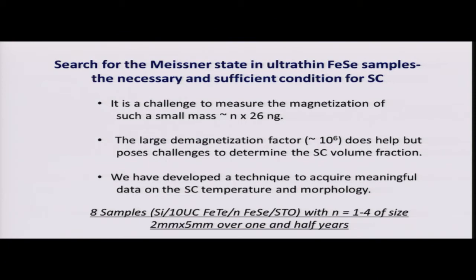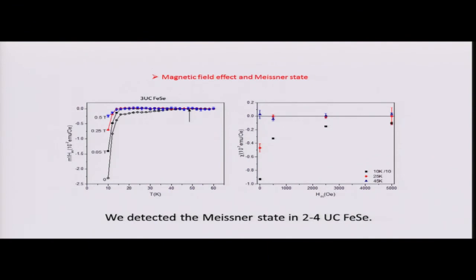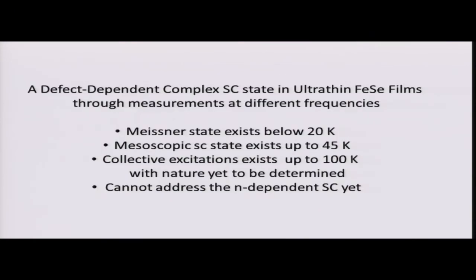One of the definitive signatures of superconductivity is the Meissner effect. So therefore, we decided to look at the Meissner effect. Indeed, we saw the Meissner effect in this material, as you can see in this magnetization as a function of field measurement. I'm not going to bother you with the details. So it is superconducting, but that Meissner effect only exists below 20 degrees Kelvin approximately. And then up to 45 degrees Kelvin, we saw mesoscopic superconducting states exist in this material. And we also saw collective excitations exist up to 100 K. And so the nature is not yet clear. In their announcement, they said one layer is superconducting, two layers not superconducting. Our experiments at this moment cannot determine that question.